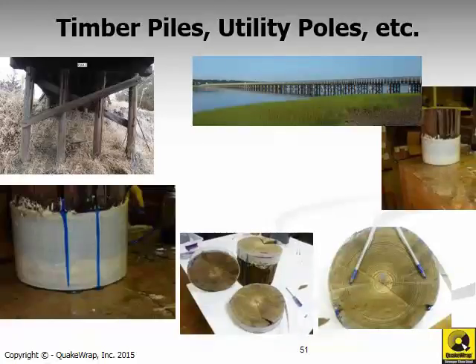As you can see here, once that resin had penetrated into the wood, we cut slices through that wood pedestal, and there are some cracks that would not normally be visible, but the resin has found its way through those cracks and filled all of them. Now we have a very strong structure because it has become solid and doesn't have any voids. Keep in mind that if the compressive strength of wood is about 3000 psi or so, the resin that we fill it with has a compressive strength of 7 to 8000 psi. So any void that is filled with this resin gives you more strength. Secondly, the confining pressure from wrapping PileMedic jackets around this timber pile also increases the strength of the wood significantly.